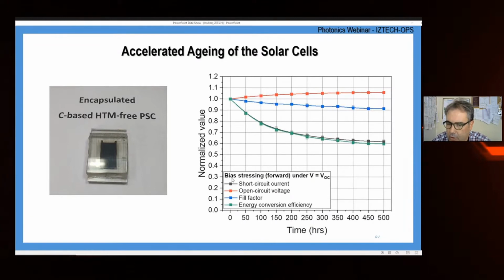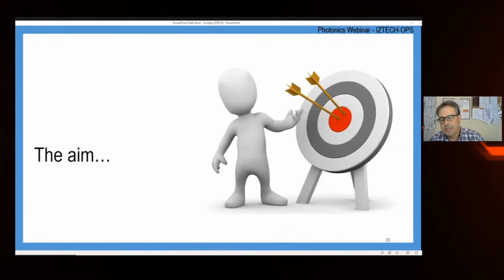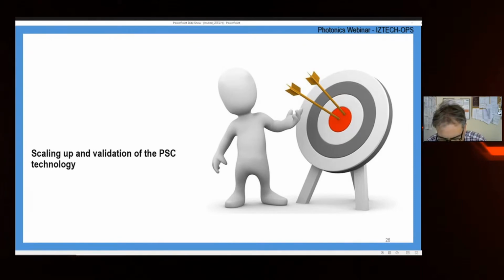We have also a test with bias stressing, exposed at open circuit voltage. We have a decrease in the current after 500 hours, and of course we have the same behavior with energy conversion efficiency. And this is the test that we perform according to the internationally accepted ISO tests. Now the scaling up.